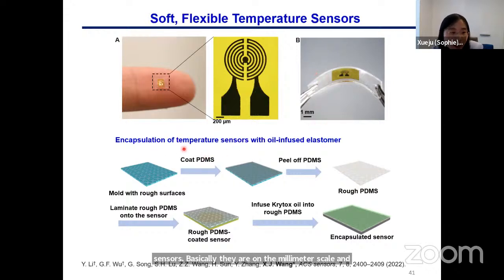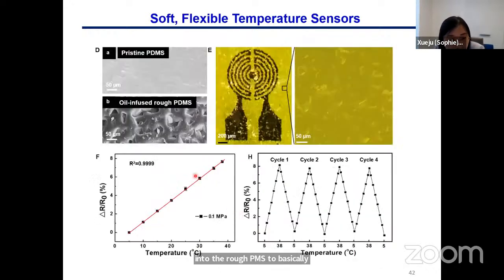In addition, to enhance the encapsulation capability of the sensors for operation in a harsh ocean environment, we developed an oil-infused rough elastomer layer, which is prepared by coating PDMS onto a rough mold, and then infusing oil into the rough PDMS to create this layer. This SEM image shows that the oil-infused rough PDMS is highly porous, and it also sacrifices some of the transparency compared to pristine PDMS because of its roughness and porosity. I will discuss the encapsulation capability for this material later.